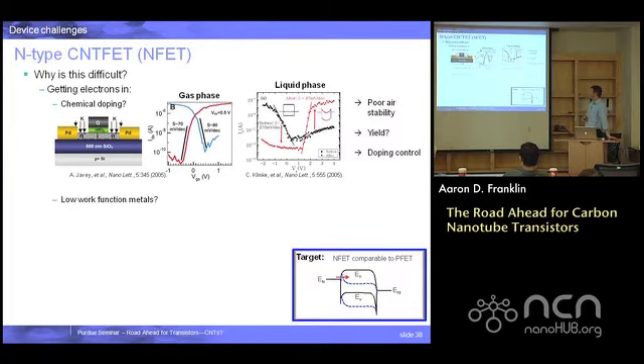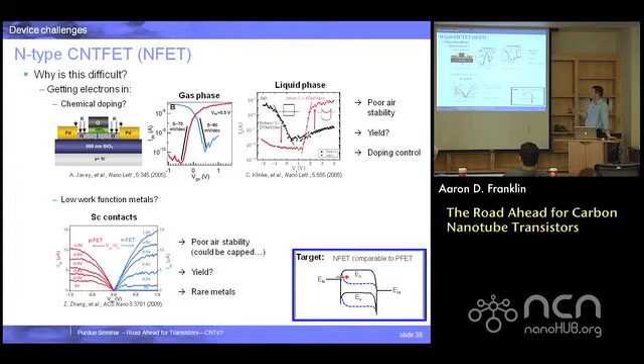So what's happened most recently is people have looked at low work function metals, which creates the picture that I show in the bottom right here, sort of the inverse of the PFET. But there's poor air stability. If you've ever worked with these materials, if you have them in an evaporator and you have them exposed to air and you come back a few days later, you'll probably have a little crucible of powder left in there. These are very temperamental metals. And so you have to be careful about how to use them and how to make sure that your yield can be consistent, because they're going to oxidize.